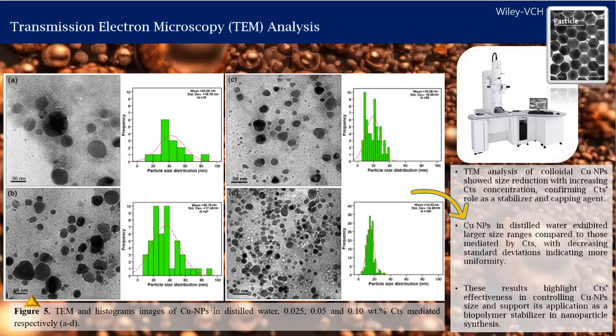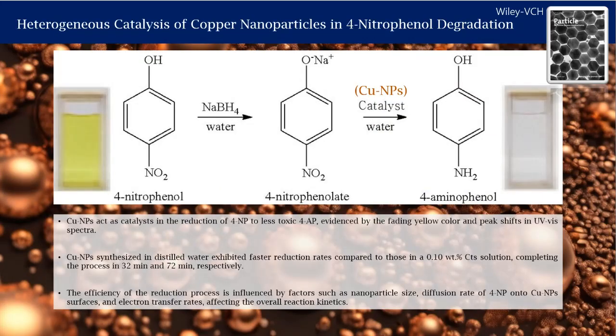Transmission electron microscopy analysis showed size reduction of copper nanoparticles with more chitosan, confirming its role as a stabilizer. Nanocopper in water have larger size ranges than chitosan-mediated ones, showing more uniformity with chitosan. Chitosan effectively controls copper nanoparticle size, supporting its use as a stabilizer in nanoparticle synthesis.